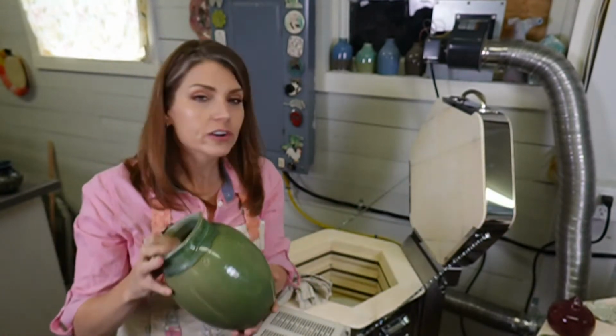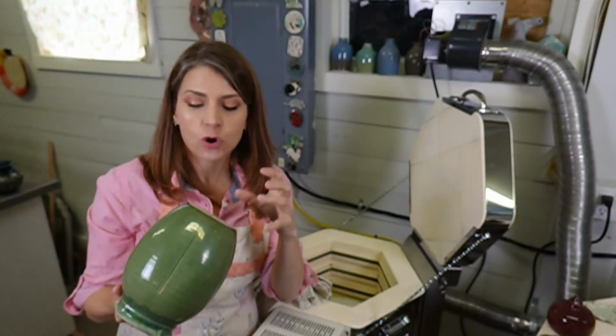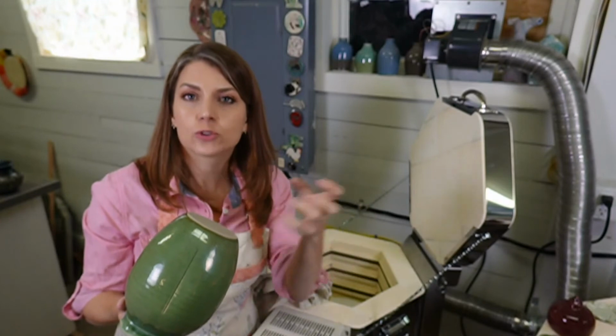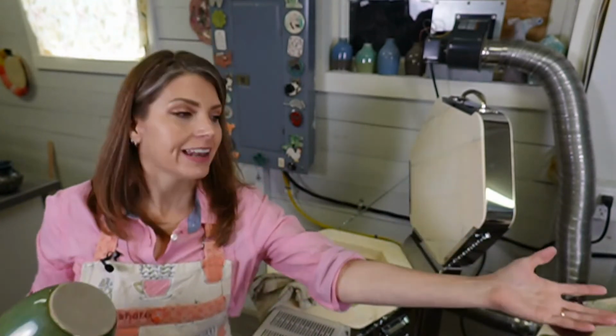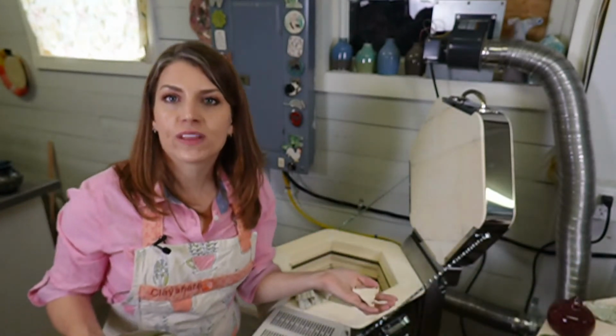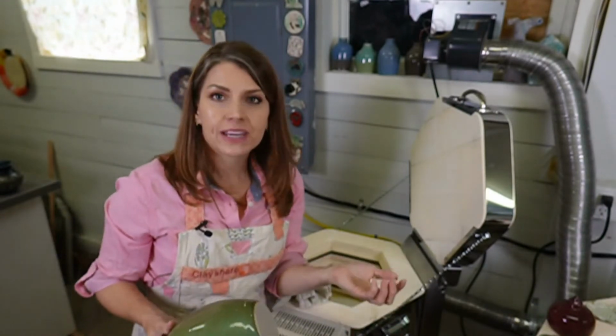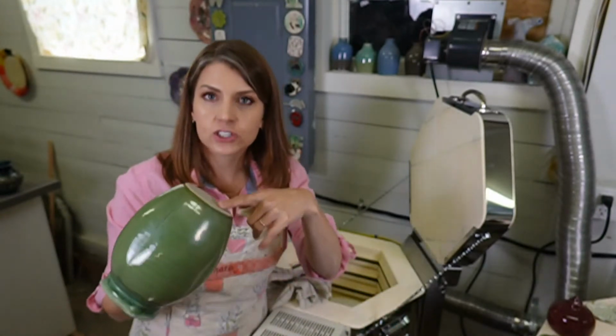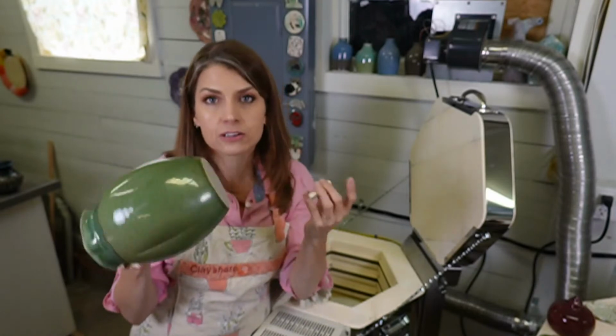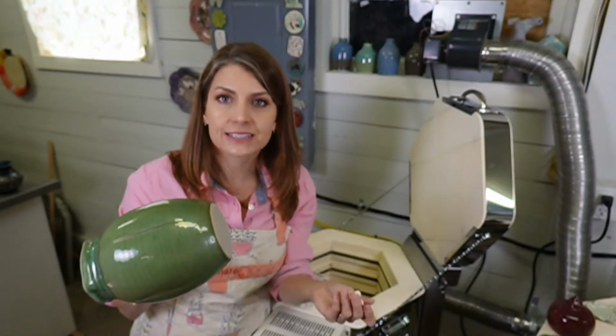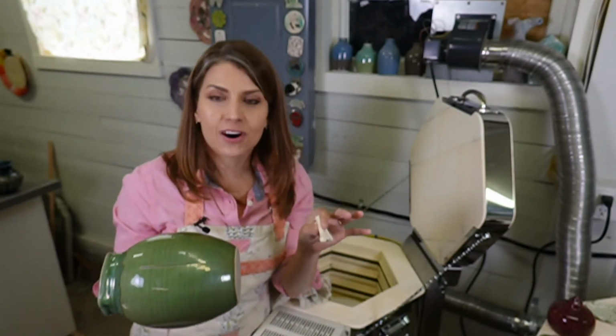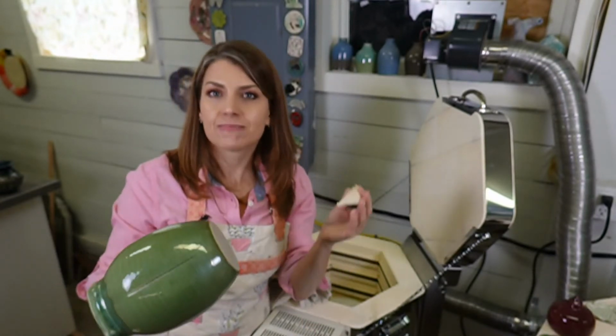So when you do earthenware, you need to glaze everything because you don't want water getting into the clay. What happens with earthenware is it'll absorb water because it's still porous, and then bacteria can grow in there, and that's the big issue. So when you're making something out of earthenware, glaze your bottom and you stilt it. Now this is for earthenware. I do not stilt high fire pieces because they warp. They tend to buckle or warp. You'll find that out with plates. Now jewelry and small Christmas ornaments, you can stilt at higher fire temps, but big plates, I don't stilt.